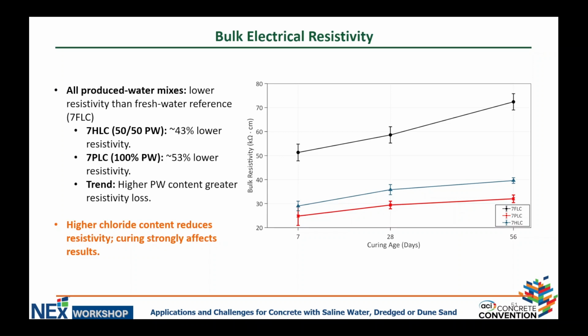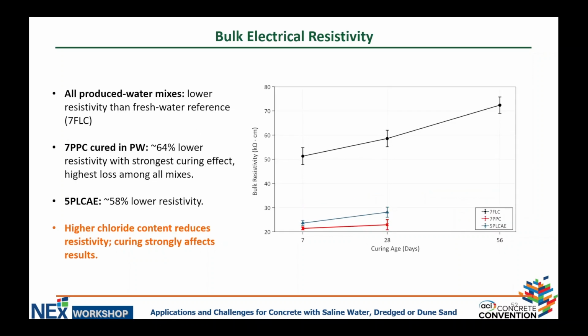But anyway, there is a decrease of 43 to 53% in the case of these identical mixes that have only one difference, which is the mixing water. Here again, we can see the same thing, but with the two other mixes. Again, the mix that was made and cured in produced water showed the highest decrease in electrical resistivity, of about 64%.